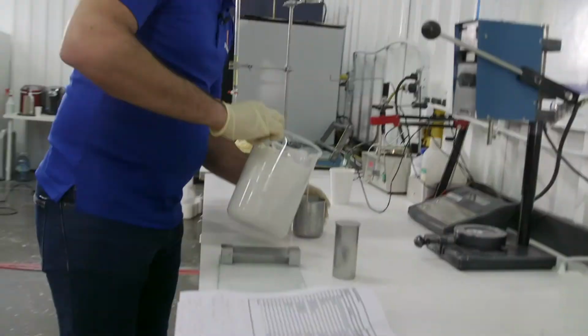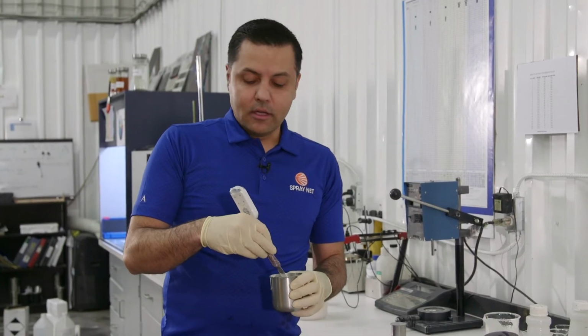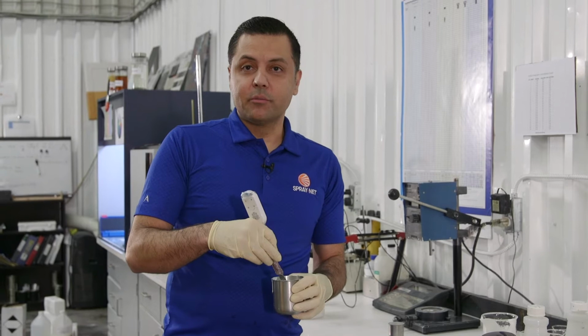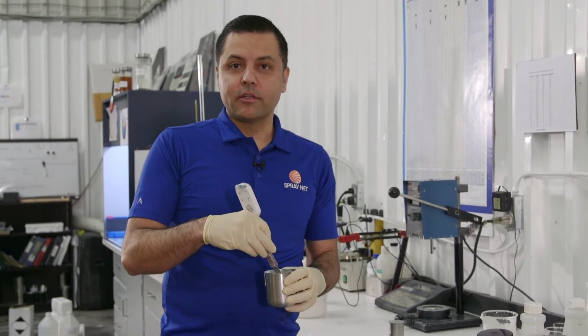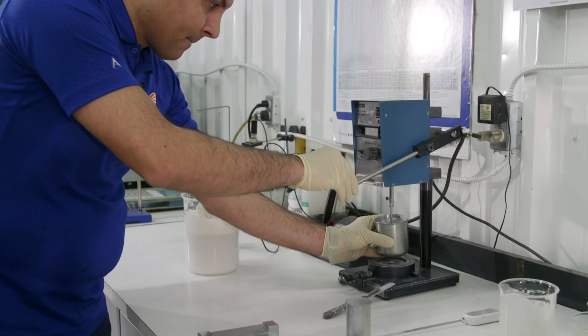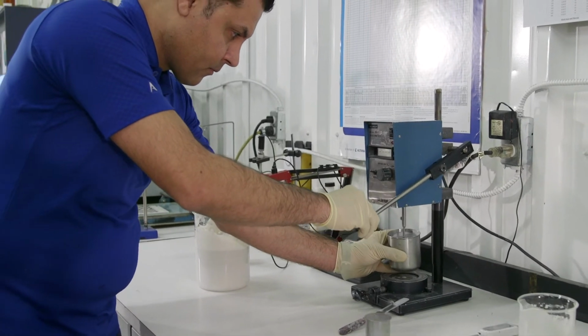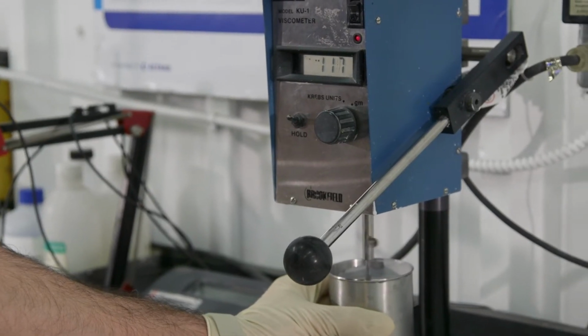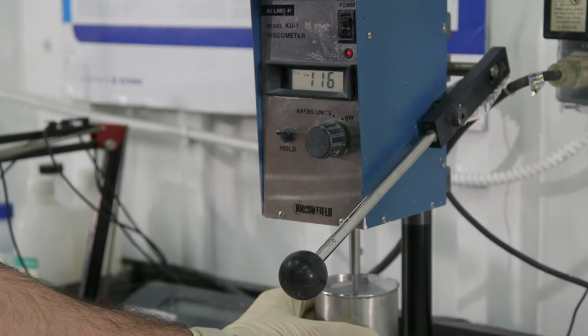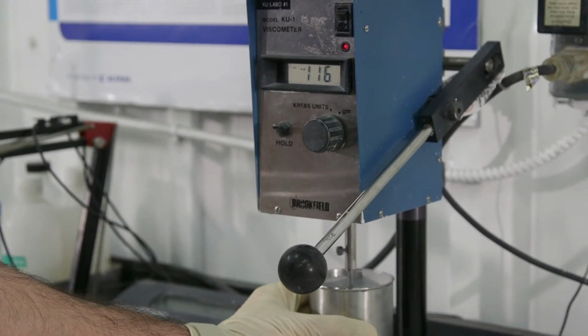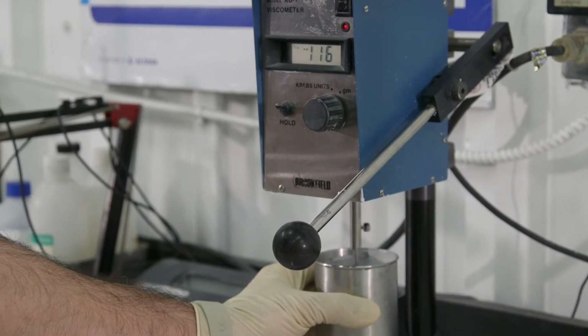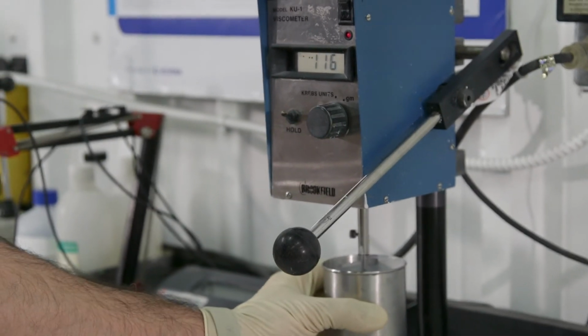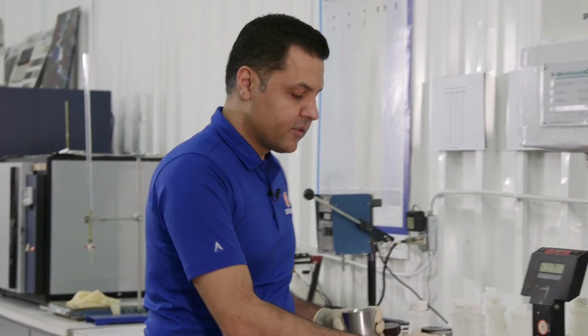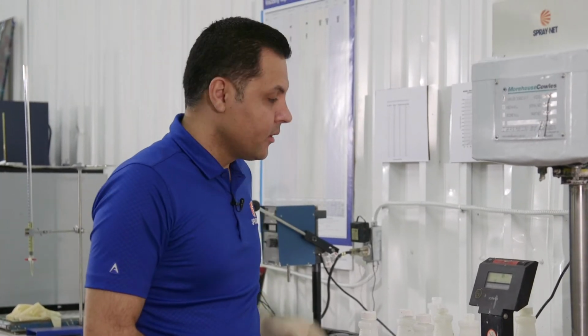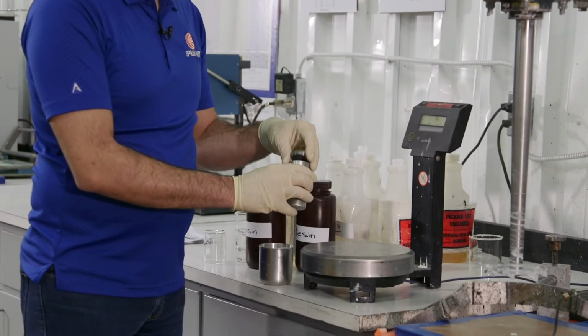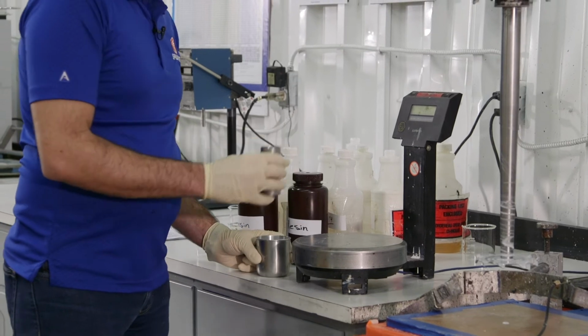The first test that we are doing is the viscosity. We always adjust the temperature at 21 degrees, which is the standard room temperature, and after we check the viscosity with the viscometer. The number that the machine shows here is the viscosity of the clear base based on the Krebs unit, which is KU. So the second test is density at the same temperature, 21 degrees, and we do it with the density cup.